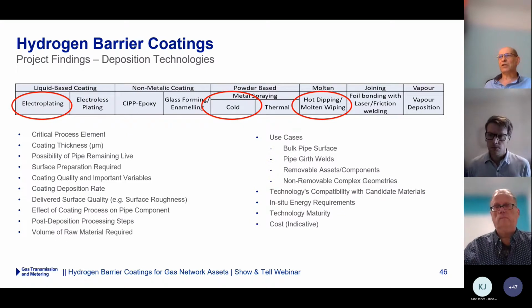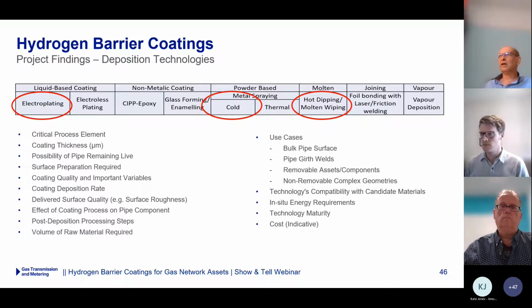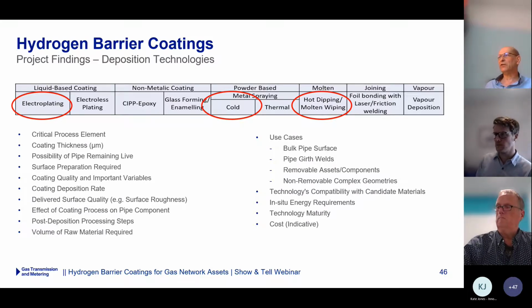These processes were considered in terms of the most critical use cases that Rob was talking about just now, that National Grid had identified, and whether it's possible to apply them, for instance, in the pipeline while it's still live with gas. Of these techniques, the three outlined here in red were considered as potential for further development for different types of assets, and this includes electroplating, cold metal powder spraying, and potentially hot dipping. Could we have the next slide, please?